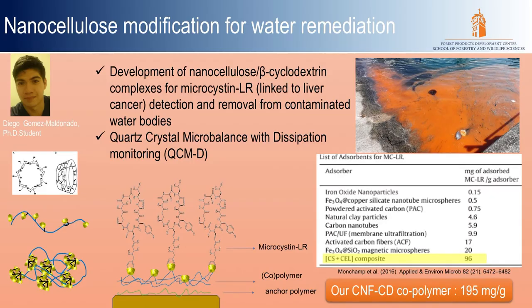The last example is related to the previous work — we are modifying nanocellulose fibers with polymers to create a new material that will allow us to adsorb and detect microcystins, the toxins from algal blooms, which many of us are aware of from the issue with algae blooms in Florida. When this algae blooms in the water, it generates toxins that persist even after the algae dies, are extremely difficult to remove, and are very harmful for us and wildlife. Our nanocellulose-based system using the QCMD detection approach can take up about twice the amount of toxins compared to other cellulose-based systems currently available.